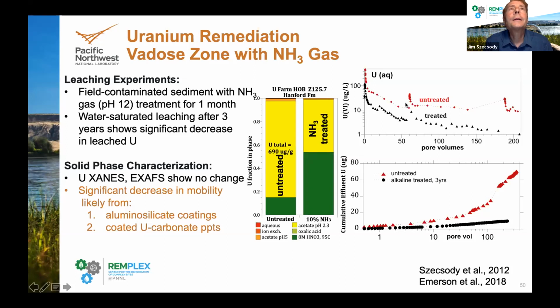Here's the it works slide, column experiments of untreated and treated sediment after 3 years, and you can see there's a big difference in leaching. These sequential extractions show there's a big difference in the amount of mobile uranium. But when we did XANES and XAFS analysis, we actually saw no change in the uranium oxidation state and the elements nearest uranium. So what was initially uranophane was still uranophane. So that's why we hypothesized that the mechanism that causes the decrease in mobilization is aluminosilicate coatings.